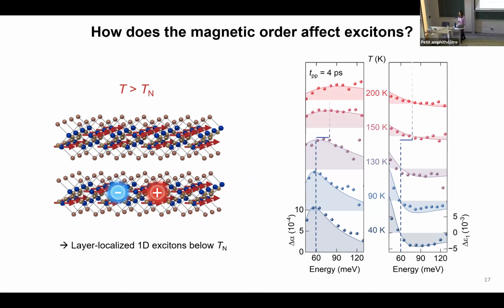What is going on actually here? The broadening is giving us hints that there must be a lot of scattering phenomena at these temperatures. And why is this happening? Take a look at the ferromagnetic state. Now, if an electron wants to escape from one layer to another layer, it can easily do it because there is no spin forbidden transition.